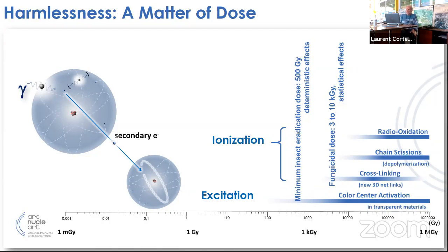We know that. Then, depending on the type of material, at about tens of kilogray, you can have what we call cross-linking, new bonds between molecules that can be understood as a kind of stabilization of the material, but it is also a modification of the original material. And then at higher dose, we will have scission and radio-oxidation, which are obviously kinds of deterioration. So this happens, let's say, after tens of kilogray. So we see that we can use safely 10 kilogray for most of the material.